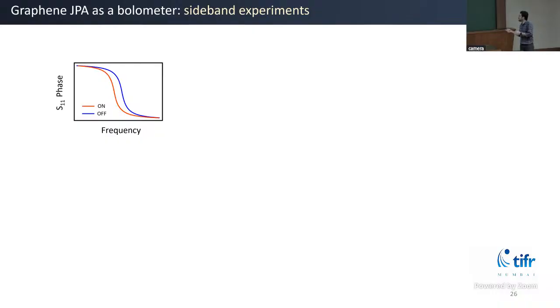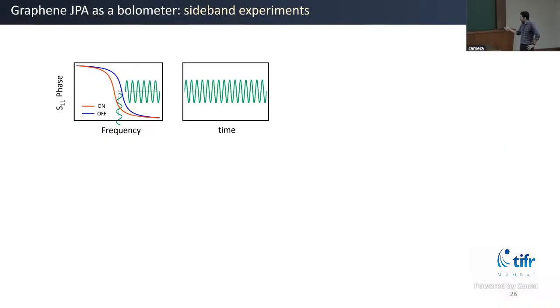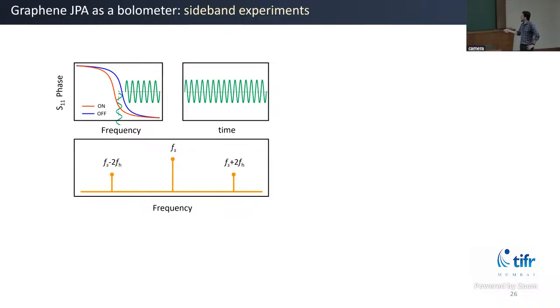So to simply say, if you have a resonator, now you are perturbing the resonance condition by sending this heater current, but instead of a DC heating, which is just the on and off blue curve, now you put a sinusoid on this heating. That means you are doing periodic heating on the heater port, and that will perturb your resonance frequency, and now you'll see these sidebands.